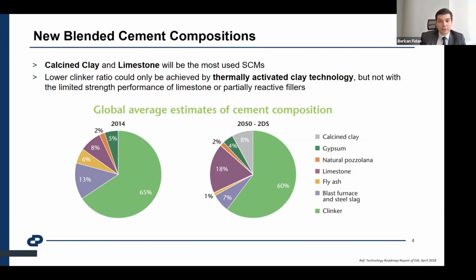The main component of cement is clinker, as we know, at 65%. And the other components, besides gypsum, which has to be there, are, as you can see, limestone, fly ash, blast furnace slag, steel slag, and some natural pozzolan. But the natural pozzolan amounts are located in different regions, and its abundance is not so effective. It's less in some regions around the world, and reserves also start to deplete. On the other side, the most used ones are blast furnace slag and fly ash. As we know, because of the CO2 actions, these plants also start to close, and the secondary output of fly ash and blast furnace slag will also decrease in the next years.